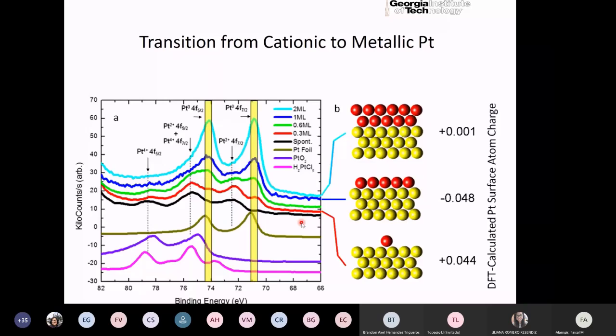The question then is, are we sacrificing activity when we do this? Because if we are getting a very high stability, but we actually do this at the cost of very low activity, that wouldn't be really useful. But it turns out that that's not the case. We have the full activity of the platinum catalyst that we expected without graphene. So if we had no graphene, the amount of activity we would have expected, we have essentially the same activity when we have the graphene on top.